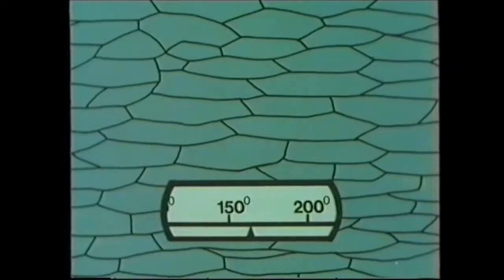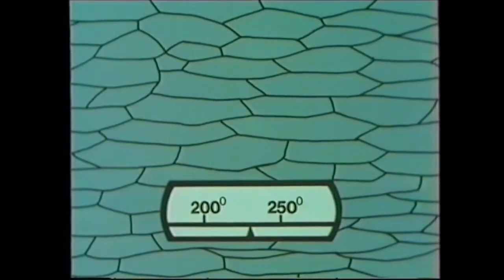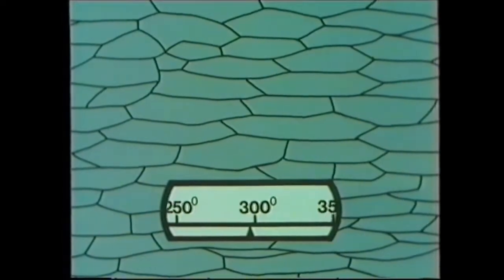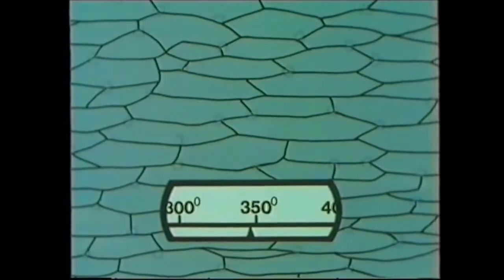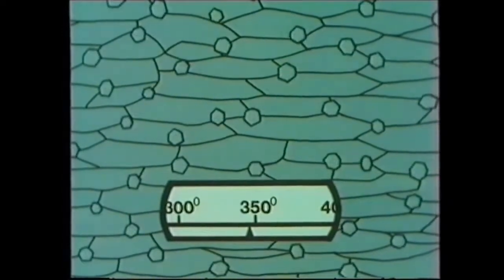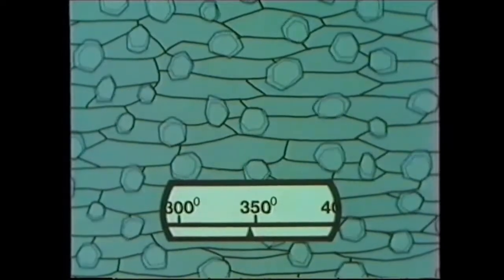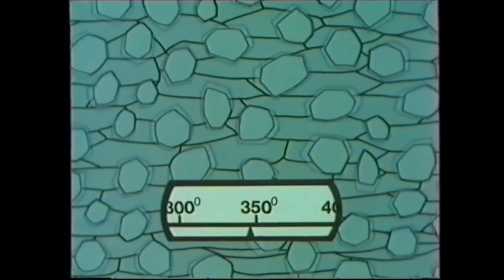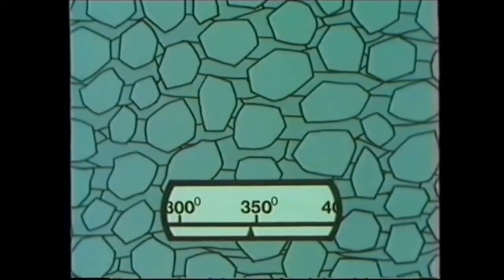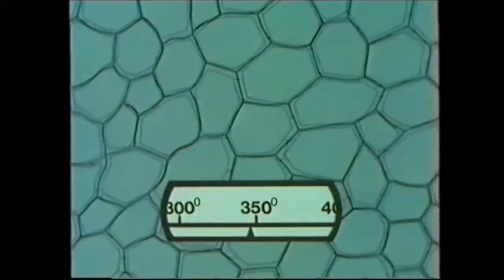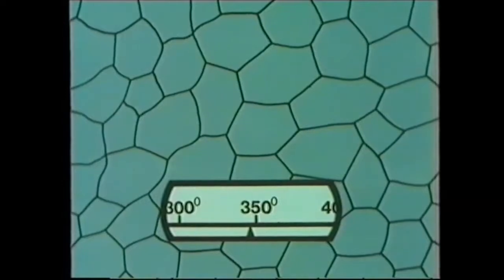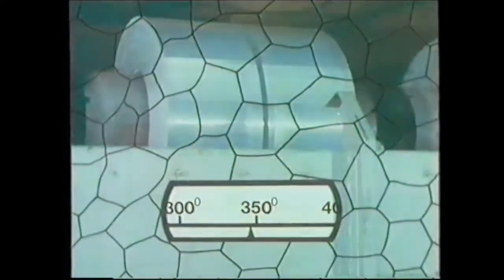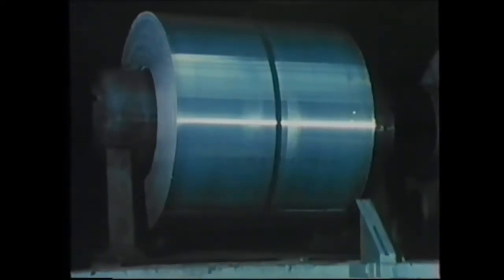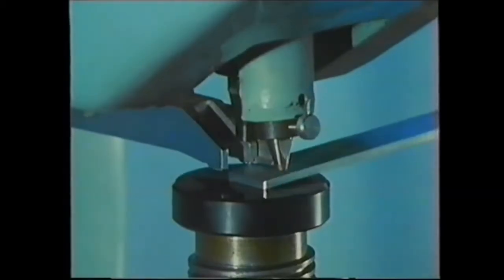In the case of this particular metal, nothing happens until the temperature reaches about 350 degrees centigrade. Now, at the grain boundaries, new grains begin to form. These grow rapidly until a new, undistorted grain structure completely replaces the old, distorted one. We call this process recrystallization. Now let's see what effect this has had on the mechanical properties of the aluminium. Hardness, for example.